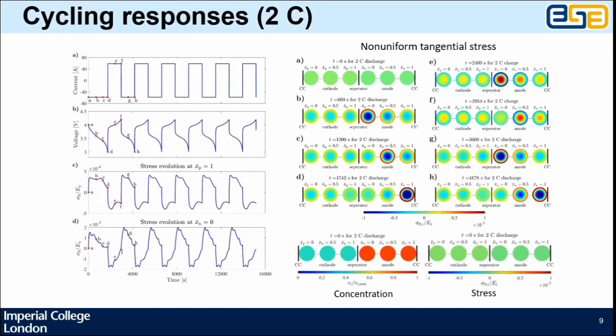We have calculated the cycling response of voltage stress in both electrodes. And on the right-hand side are the stress distributions across both electrodes at the specific time steps marked on the left-hand side. We can see that the stress distribution is quite non-uniform, and there are large stress close to the separator during charge and discharge. And when the current is changing the direction, there is also large stress at the current collector side.